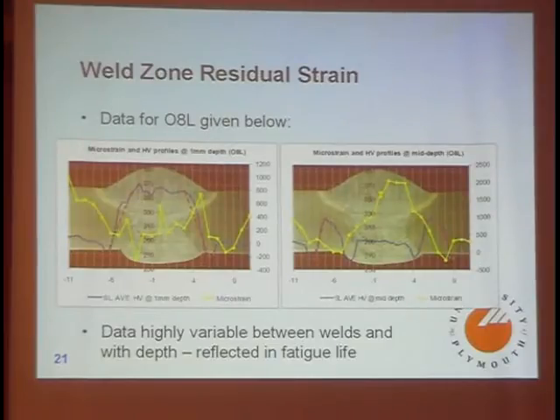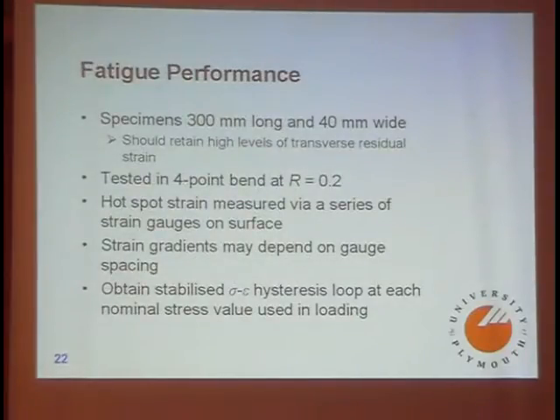And as I say, you can see that the data do vary rather a lot from weld to weld. So we've got the residual strain, we've got the micro hardness, now I need the fatigue life. I've used specimens 300 millimeters long, 40 millimeters wide, 4-point bend, R 0.2. I've measured hotspot strain by a series of strain gauges on the surface, and I'm happy to note that the sizes were about 0.5 millimeter. They correspond with what Morrow said they should, so I'm reasonably sure it's okay. We've obtained stabilized stress-strain hysteresis loops at each nominal stress value used in loading.